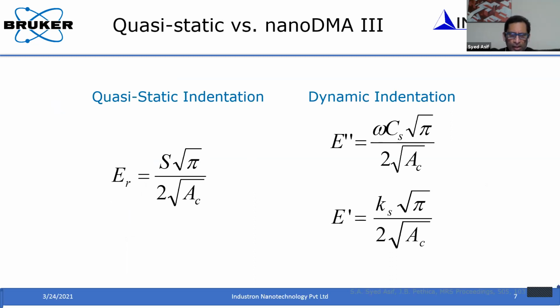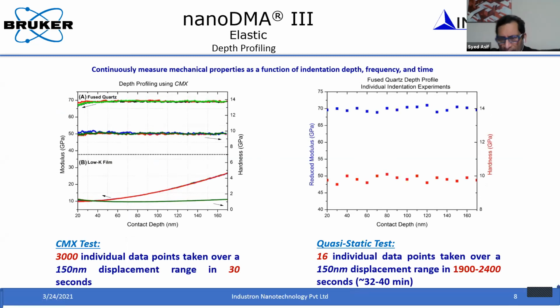Now, in the quasi-static indentation technique, you basically measure what we call the storage modulus, or the reduced modulus of the material, by measuring the stiffness. In dynamic indentation, like I mentioned, you can measure both the storage and the loss component. Okay, so if you do it on an elastic material, what you measure is the stiffness as a function of depth, and if you convert that stiffness and depth information into hardness and modulus, you can measure this property continuously as a function of depth. So in one single indentation test, you can have hundreds of points along the indentation path.